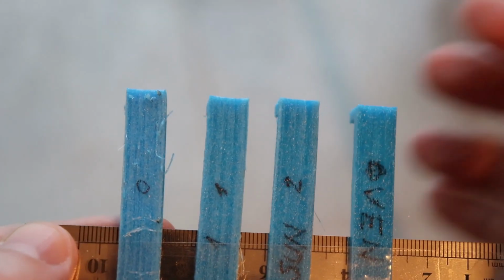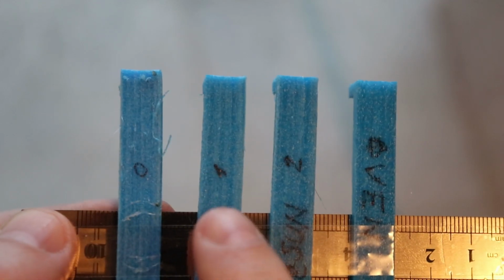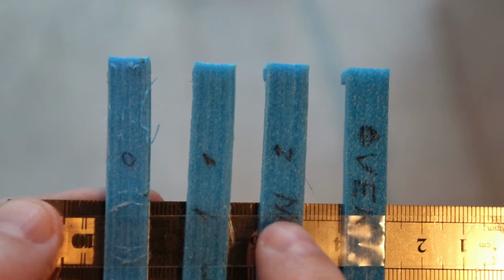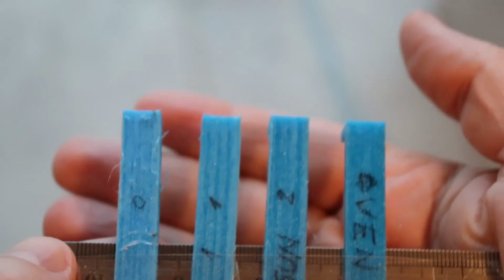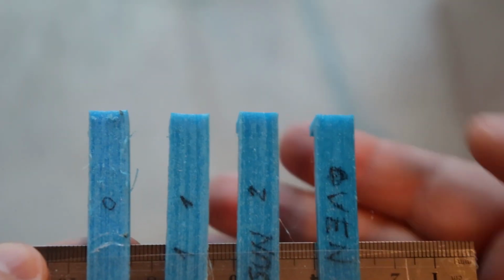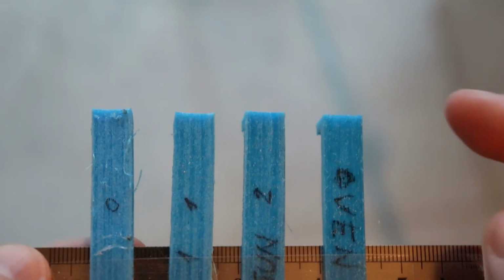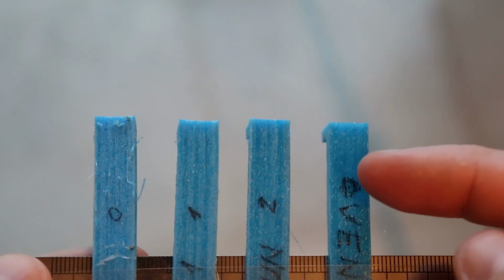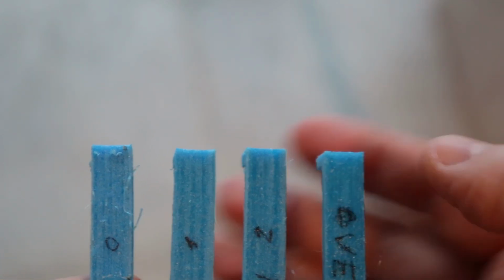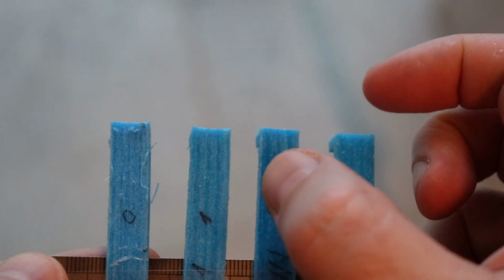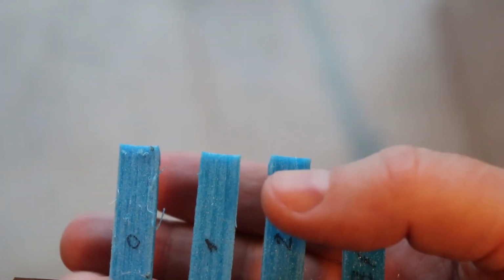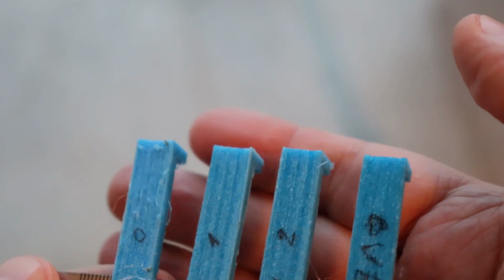And here they are side by side. So this was undried, this was dried 12 hours, this one an additional 6 hours with the rotating, and this one was dried in the oven. And here I can clearly see that this is almost dry, because there are no lines like with the previous 2 or 3 versions.